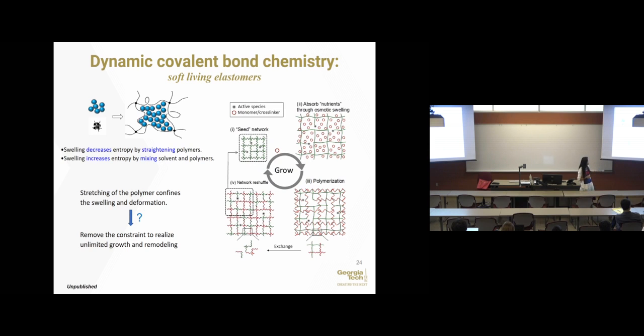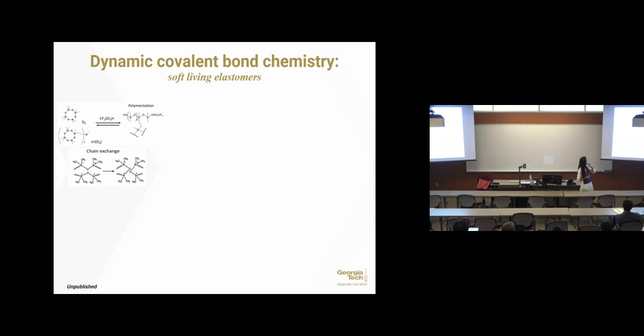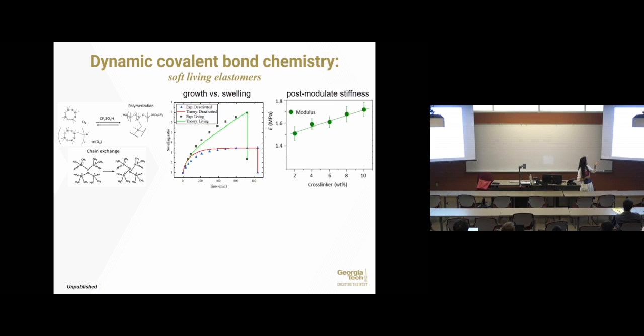So this is a schematic that in our mind, if you have these dynamic sites, the active sites, in the network, when you swell it with new monomers, this network is stretched. And it's not comfortable that way, so it opens up to let more monomers, the new network, homogenize with the old network to homogenize the stress. Now the network is more relaxed, then you can absorb more monomers and keep growing. So this is one set of chemistry we tried in the very beginning.